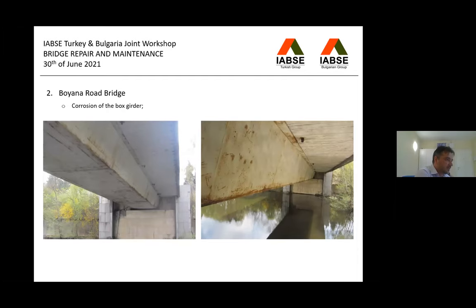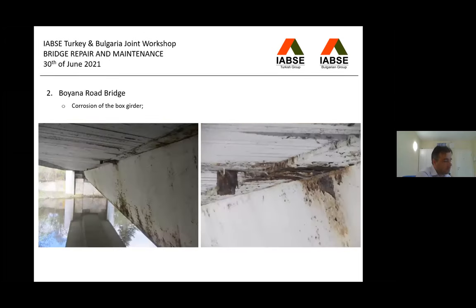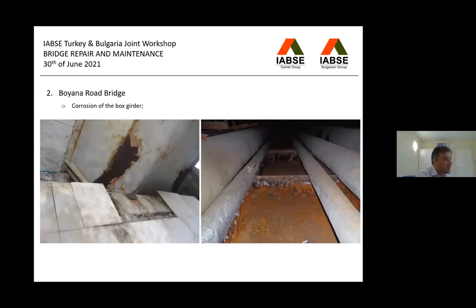If you look at the corrosion of the steel, the corrosion level of the steel box outside was actually relatively low, considering that this is the original paint after maybe 45, 47 years of exploitation. Only zones with pitting corrosion were found. The places with more corrosion were around the dewatering pipes, which were designed very short, so the water was spilling around and over the box. So we have some zones here with uniform corrosion. Also, we have some zones with uniform corrosion around the bearings of the two abutments, due to leakage into the expansion joints.